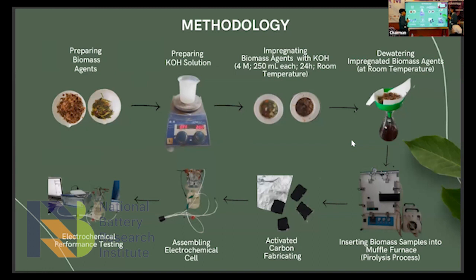So here's the methodology that we use in this research. We did the experiment and also did literature studies, where the experiment involved steps as shown in the display. First, we prepare the biomass agents, and then we prepare the potassium hydroxide solution. Next, we impregnate the biomass agent with potassium hydroxide for 24 hours with a concentration of 4 molar to increase the surface area.